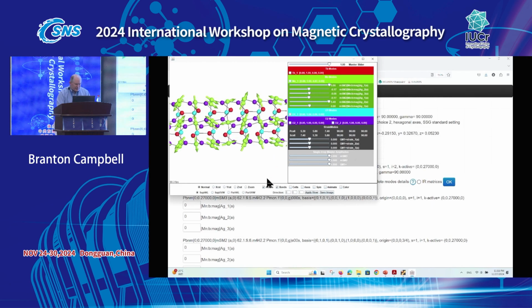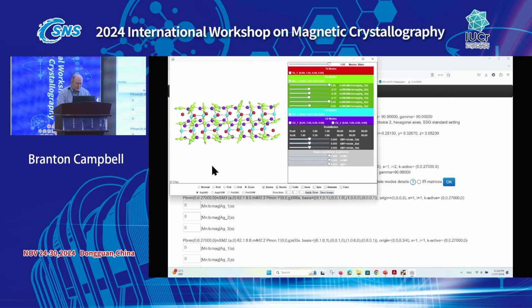And I think together you can see that it forms a cycloid. So I can't make them rotate yet, but the new version of ISOVIZ will make the phase rotate, like what you see in the JMOL examples from MAGNDATA. So we've essentially combined a longitudinal wave and a transverse wave out of phase. 2 different IREPs combined to give you this cycloidal structure.